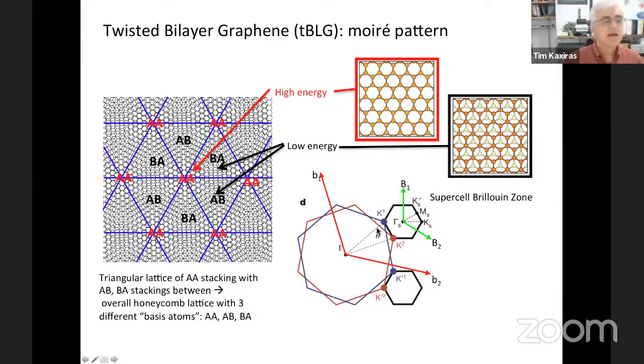And this is the standard picture in reciprocal space, where the large colored hexagons, the red and the blue, come from the two different layers. So these are the K points, the corners of the original Brillouin zones, where you have the Dirac cones, and the small black hexagon corresponds to the supercell produced by the stacking.